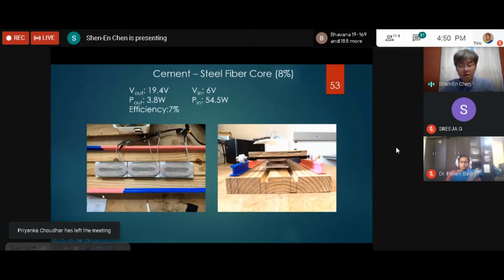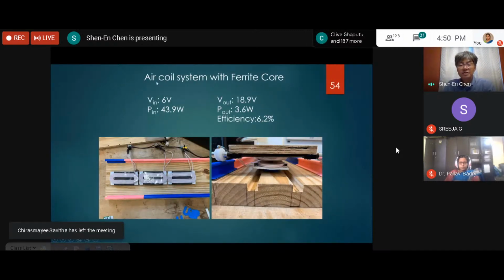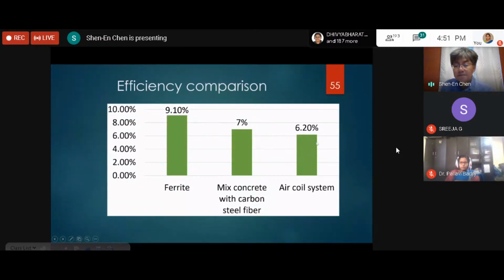When we use our steel fiber concrete at 8% fiber content by volume, we were able to achieve a 7% efficiency. So it's slightly lower than this 9%, but it's still better than the air coil case. And this is the air coil case with a larger air space, which shows only 6.2% efficiency. So here you see that with air coil, you only have 6.2%, with ferrite coil you have 9.1%, and with the mixed concrete with fibers, we reach 7% efficiency. Again, it demonstrates that concrete with carbon steel fibers was able to demonstrate higher power transfer than the typical air coil system.